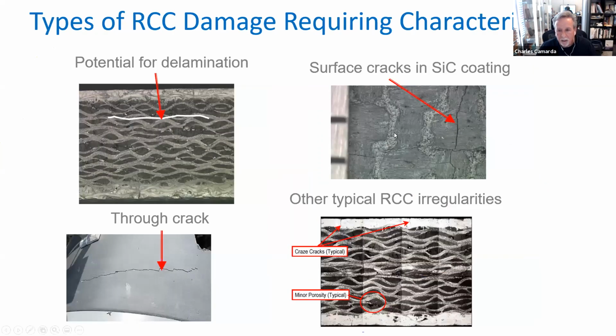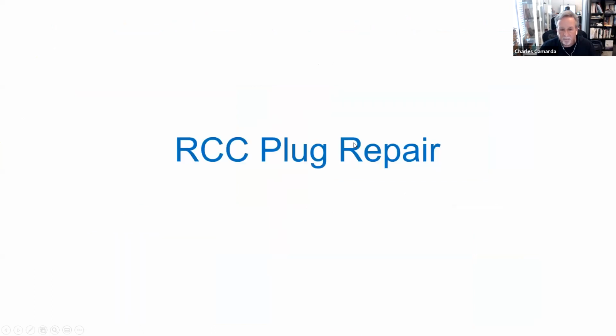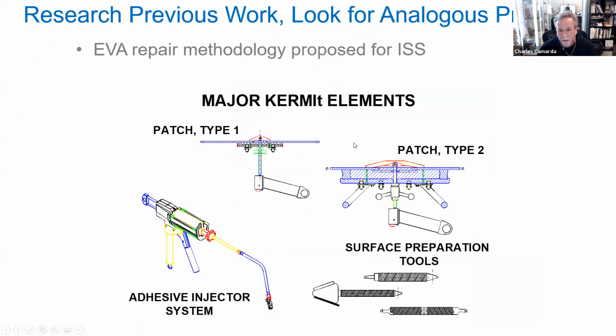We also need to understand all the different anomalies within this material. You know, there are voids in the surface, there are delaminations. What happens if you have a crack? What happens if you have coating loss? One of the things we did was we looked at ways that we could possibly repair this, right?